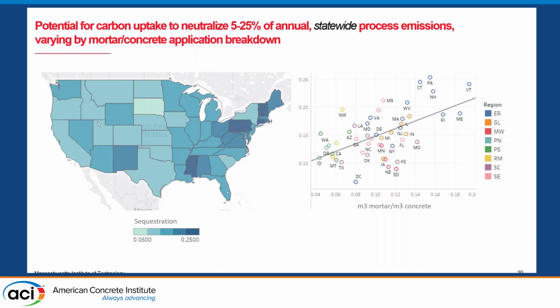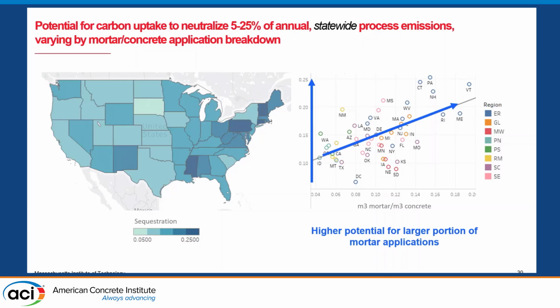Comparing the cubic meters of elements that include mortar to the volume of elements that include cast-in-situ concrete, we see that there's higher potential for carbonation in states that have a larger portion of mortar applications compared to cast-in-situ concrete applications.